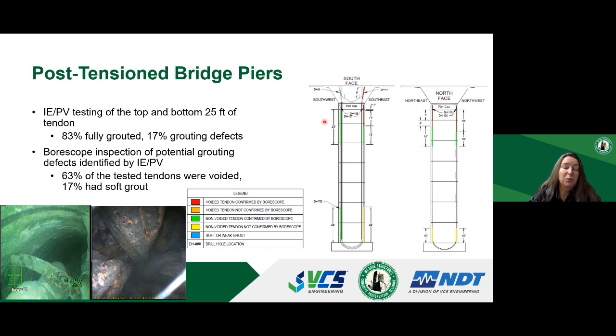So grouting defects can be benign. Those are lens voids or rind voids that do not expose the strands to the air. So the strands are fully coated. However, there is a void between the grout and the duct, and this will be picked up by impact echo testing as a potential grouting defect. While other defects, such as voids that do expose the strands and soft grout, create a corrosive environment for the strands. So based on the results of impact echo testing, we selected locations for borescope inspection, and this is what helps us to differentiate between different types of grouting defects that are identified by impact echo.